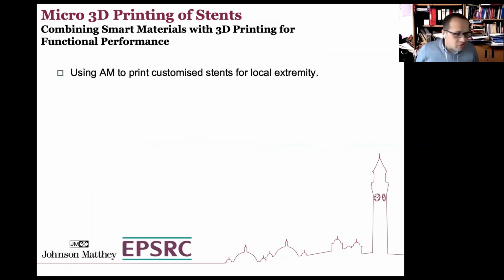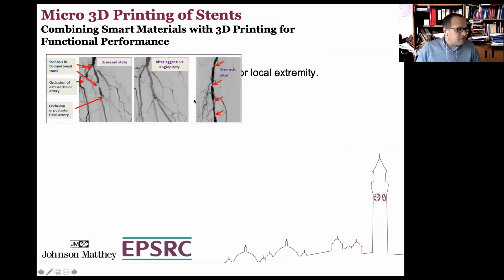This is one of our current projects which looks into 3D printing of stents. And stents, as you know, as we all get old, we end up having what's known as stenosis. So our arteries start to become narrower. And usually the cardiologist has to intervene with something we call a stent to open the arteries and allow the blood to flow normally inside the body. The problem is that in many cases they will find multiple stenosis sites. So they will start to add like 1 or 2 or 3 stents in order to open up the full artery.